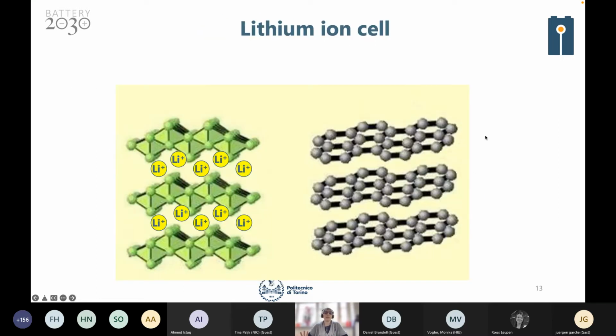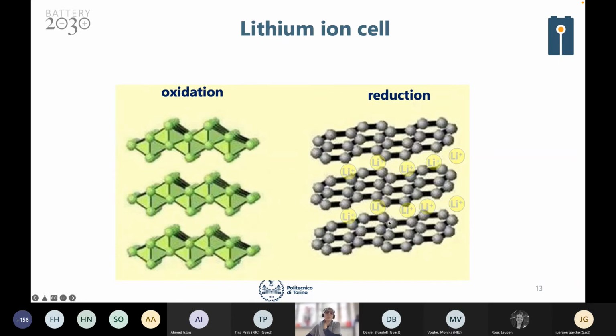Okay, so we spoke about lithium cells. In 1991, Sony commercialized the first lithium-ion cell. The difference between a lithium cell and a lithium-ion cell is related to the use of graphite instead of metallic lithium. Instead of getting the reduction of lithium ion to form metallic lithium, in this case it is graphite that is reducing, and the lithium ions are moving toward the electrolyte and will be inserted inside the graphite electrode. So the advantage is that we never have metallic lithium in the cell.